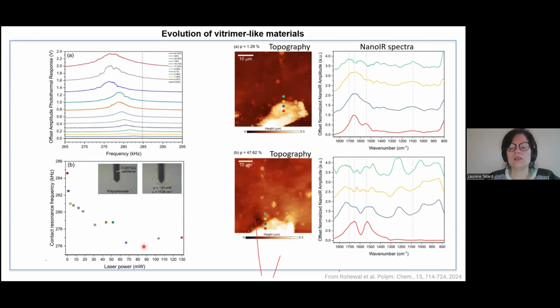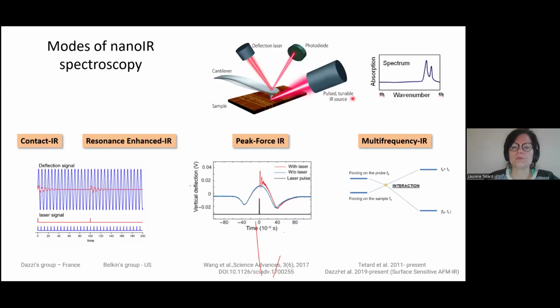But recently, the work has evolved to a little bit more complex system to study. So for instance, here we worked with researchers at Oak Ridge National Lab who are developing some vitrimer materials. So vitrimers are polymers that undergo a chemical change as you're heating them, and that changes also the mechanical property. And so we were able to show that if we're acquiring the spectra as we're heating up the sample, we can detect, so you see here it's color coded, so the red spectrum at room temperature, and here the spectrum at the red dot as the temperature is increasing. And so you can start studying how materials behave under different conditions. And in parallel, there have been lots of developments also in new modes of nano-IR spectroscopy. So all of this kind of works hand in hand, and it allows to broaden the range of application for the tool.